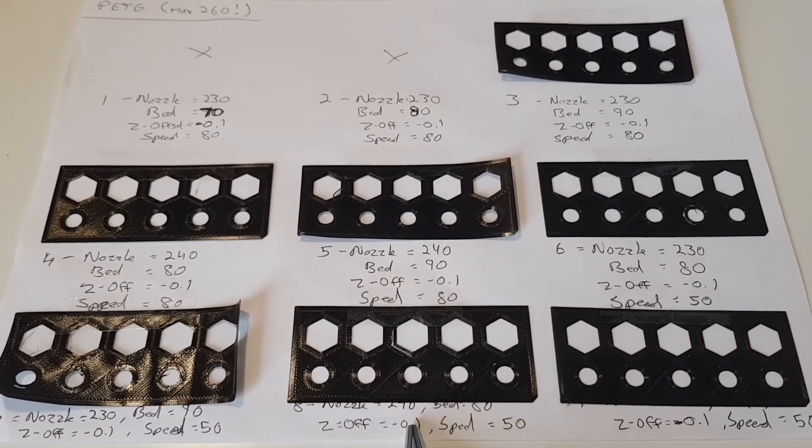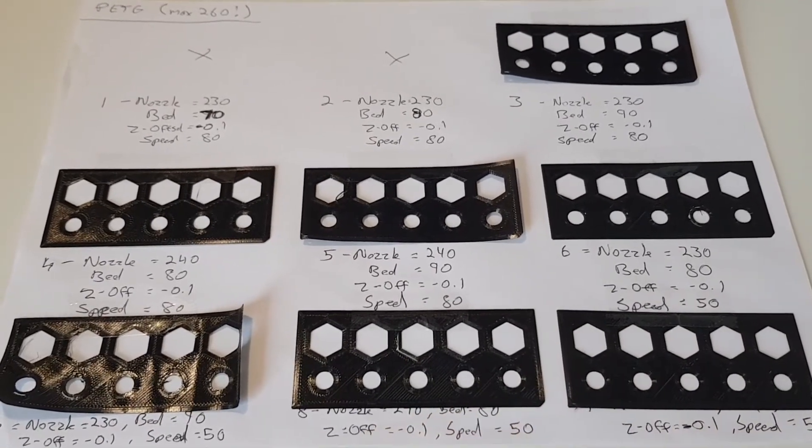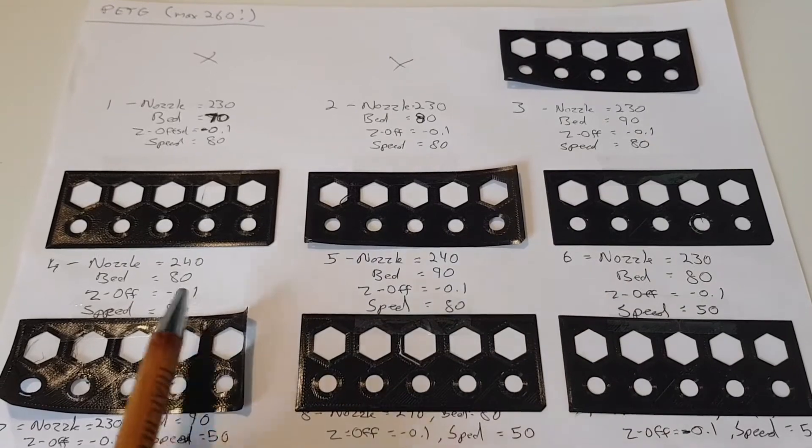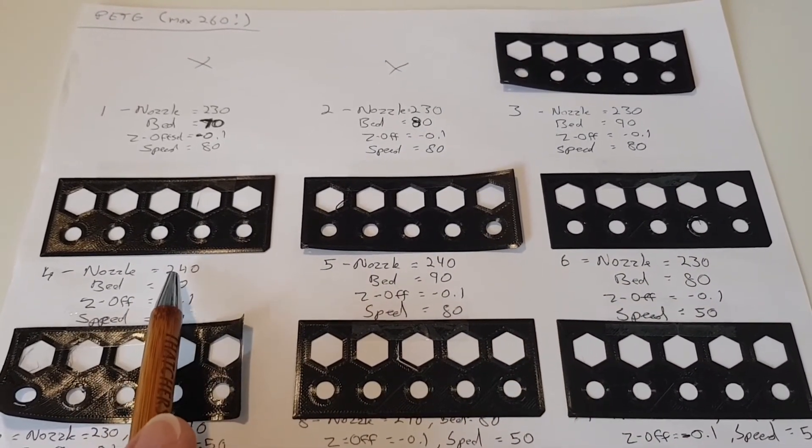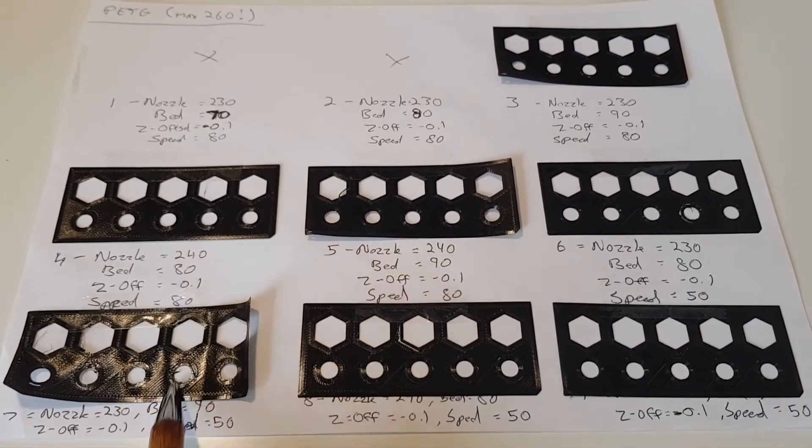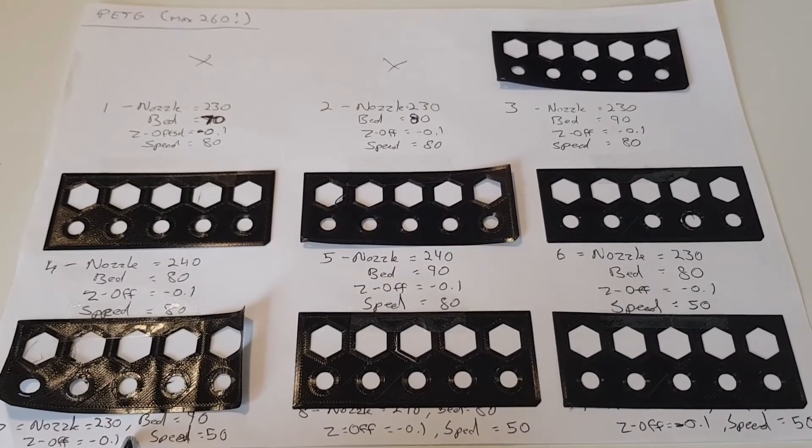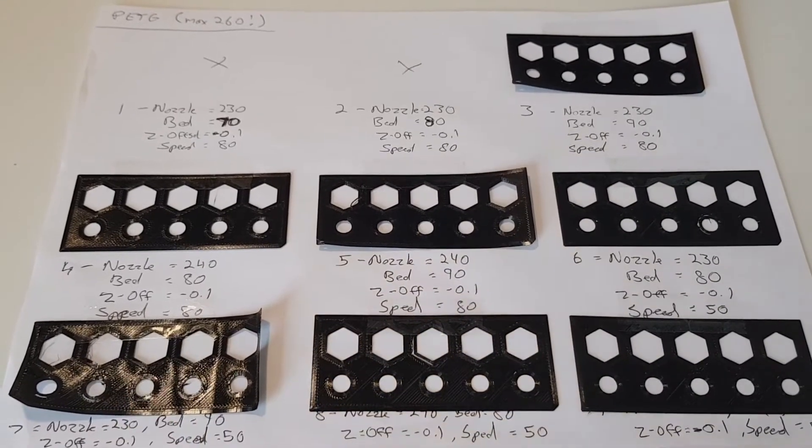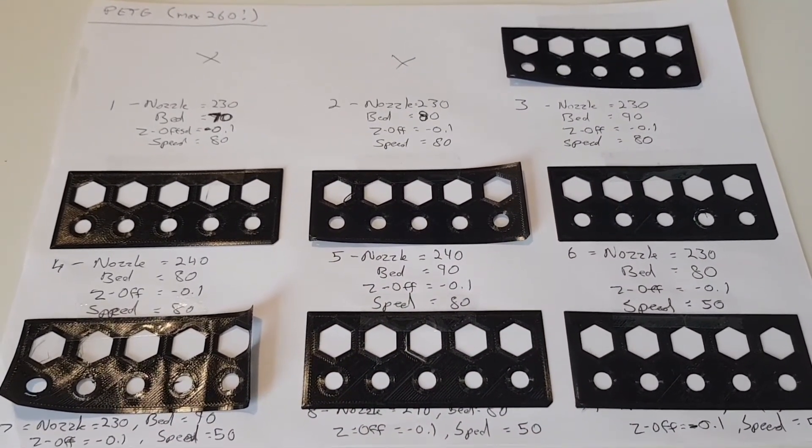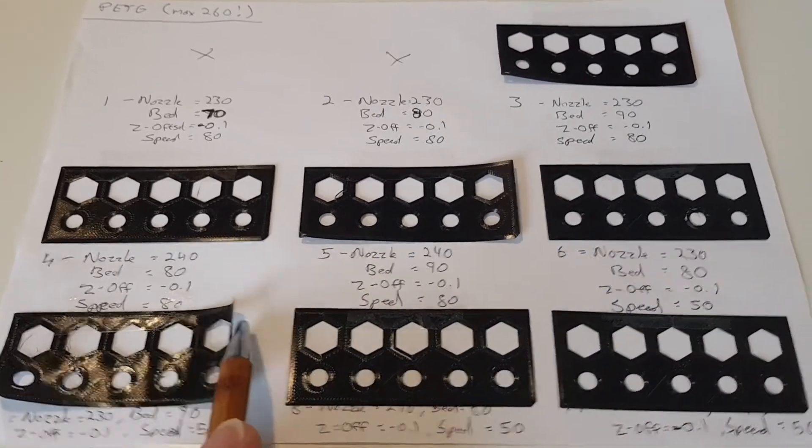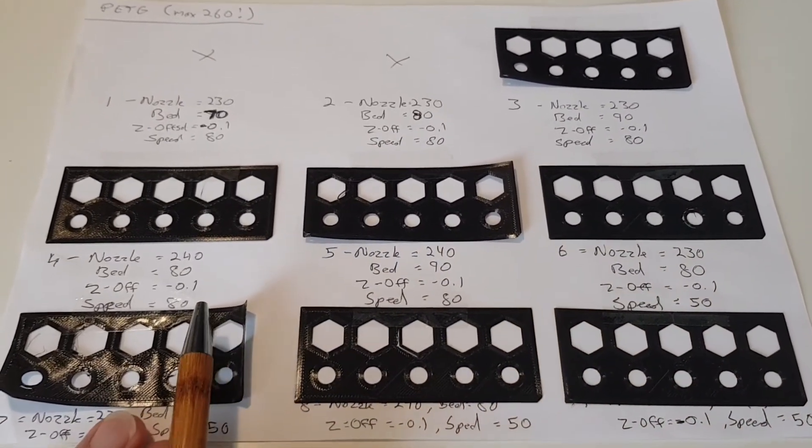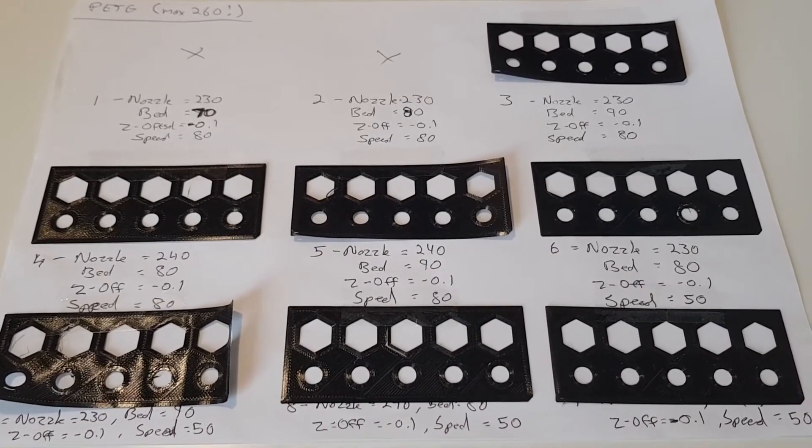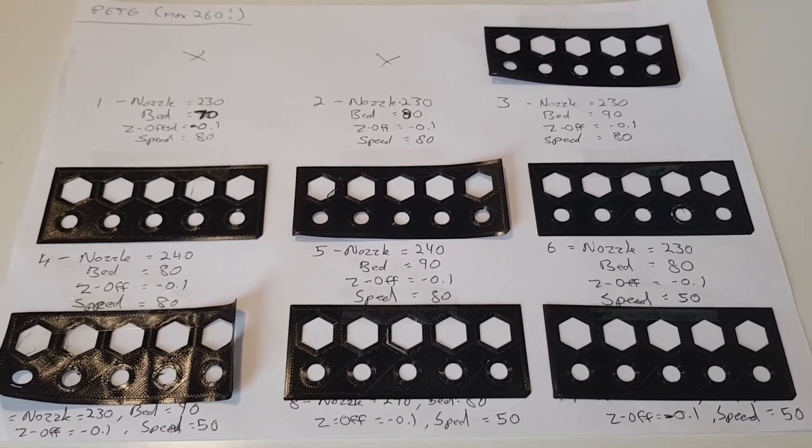I noticed that if I did go slower the quality was slightly better. So yeah, basically what this has told me is that I want the bed somewhere between 80-90 degrees and the nozzle probably needs to be somewhere between 230 and 240. Playing around with the z-offset, despite trying to level my bed I found that I just needed to have that slight bit of z-offset configured on the first layer just to make sure that it really sticks down properly and that value I was using was minus 0.1 and that's just using a standard layer height of 0.2. So yeah, let's jump onto Cura now and run through all the settings that I ended up with.